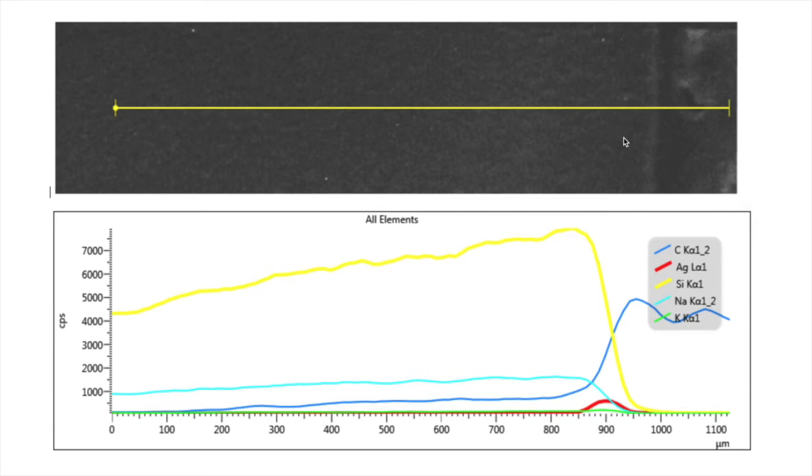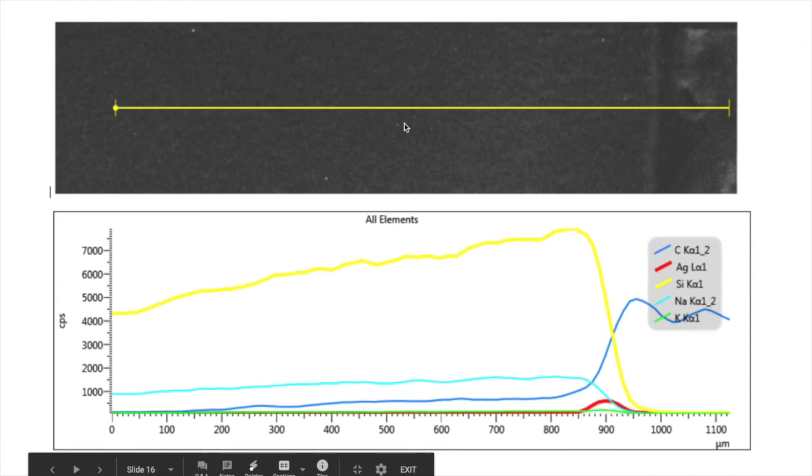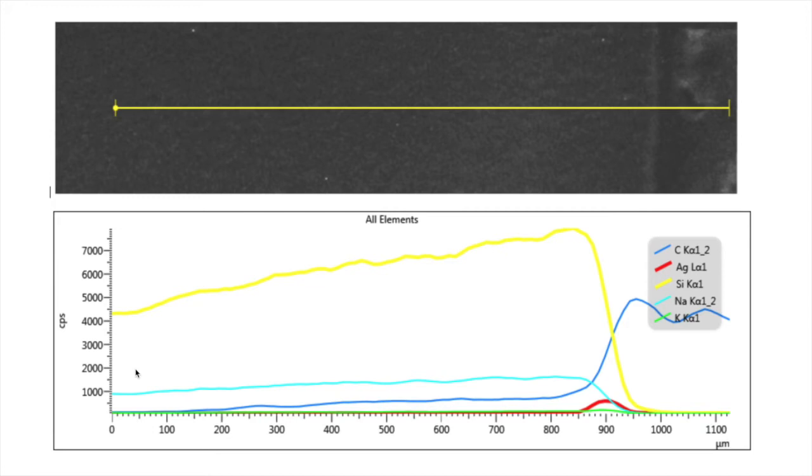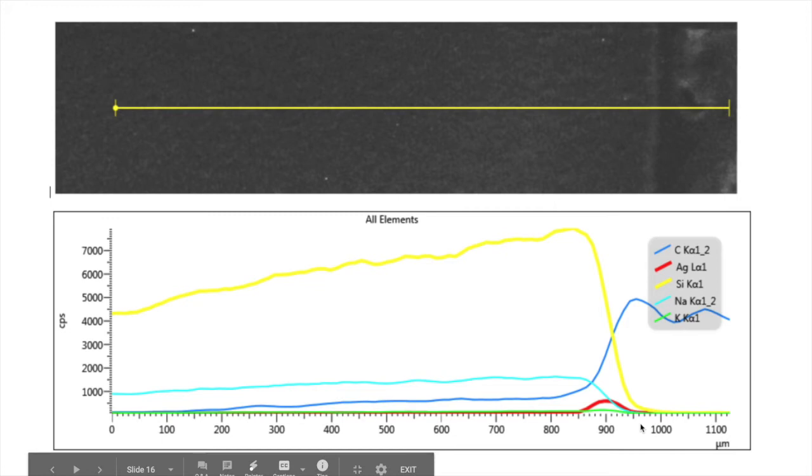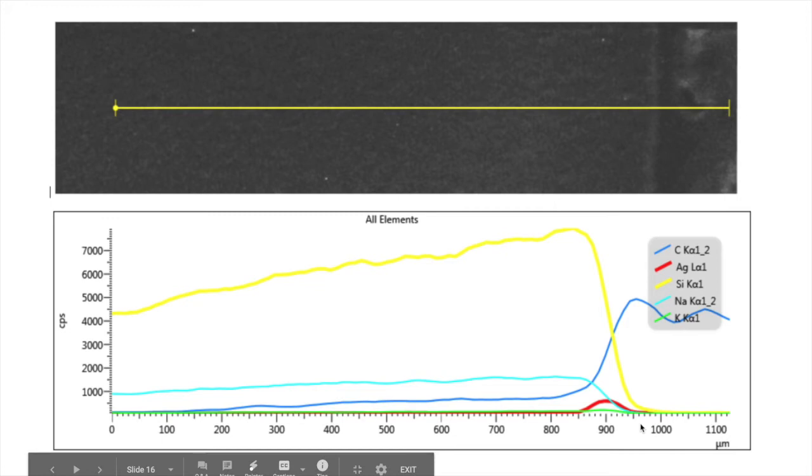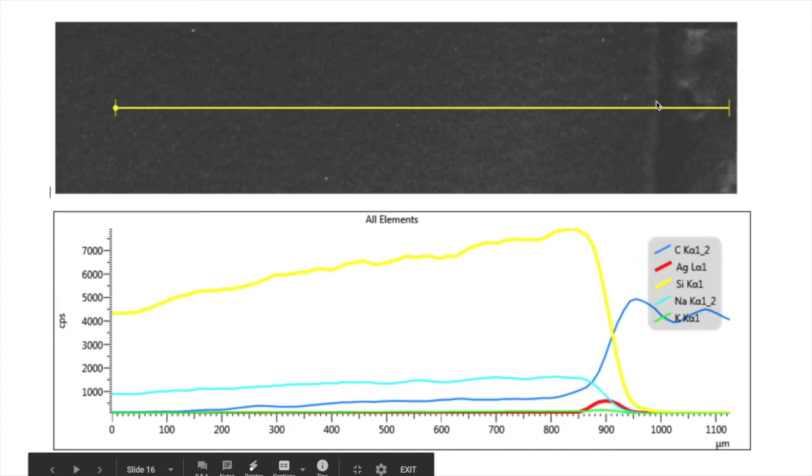So data is collected from all of these points. But with a line scan, the useful thing is instead of with an area scan where we take all of the area and basically average it, with the line scan what we do is we keep all the data points separate. And so this plot down here shows the breakdown of that. It shows us what elements we have and where along the line they are. Here at zero corresponds to this point here, and then down here corresponds to the end of the line. And so all of that data for the various points is plotted spatially. And so the usefulness here is that this glass rod has variations. Silicon, you can kind of see it everywhere, except for the surface, which is right here.